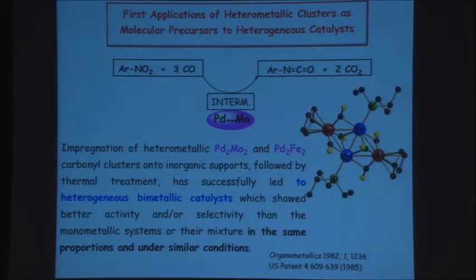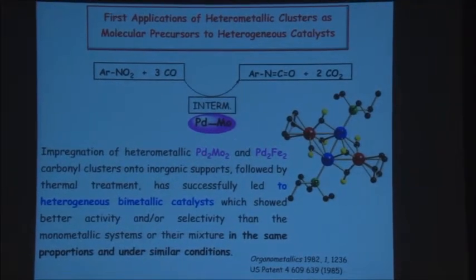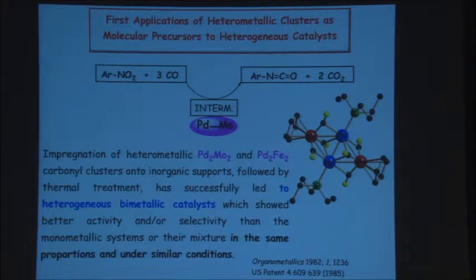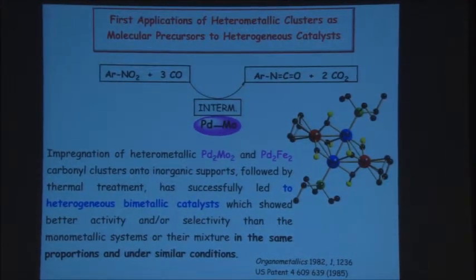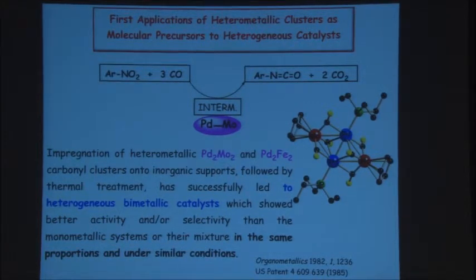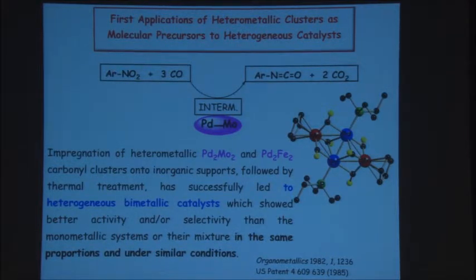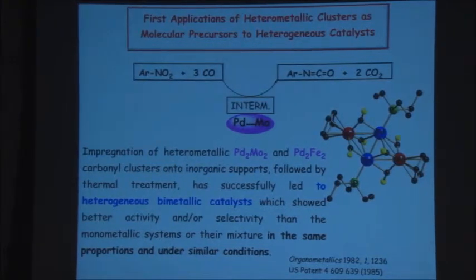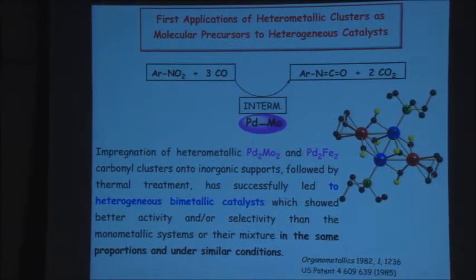So we took this cluster, the core composition is palladium-2 molybdenum-2, and tested it for this reaction, which is a carbonylation of organic nitro, aromatic nitros, to give isocyanates plus carbon dioxide. That was done in collaboration with a French company called Atochem at the time, which was a producer of isocyanates. Isocyanates, of course, are very important organic chemicals, precursors to polyurethanes, etc., tons here. The classical way to make isocyanates is to use amines plus phosgene. Well, even if you're not an experimental chemist, you've heard of phosgene. It's usually bad news. It's not very green in terms of the surrounding. Industry can handle phosgene. But if we could have a milder way to get to isocyanate, that would be nice.